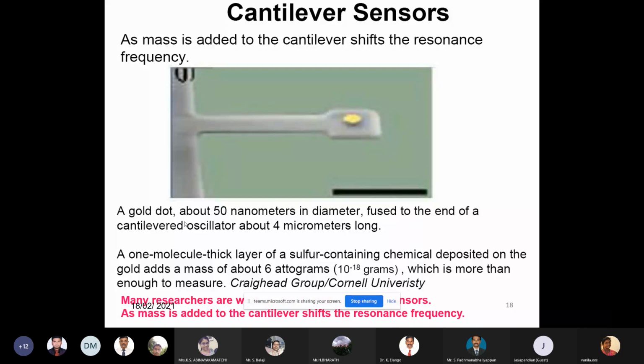Just imagine, with a simple cantilever structure, the Cornell University people proved 10 power minus 18 grams, 6 attograms measured. Minus 18, just imagine. Now, recently, people reported minus 21, zeptogram, and even yoctogram, measured with a nanostructure cantilever. Here, all researchers use the resonance frequency shift in vibration mode. That is the dynamic mode of cantilever operation. This leads to a number of sensor applications.